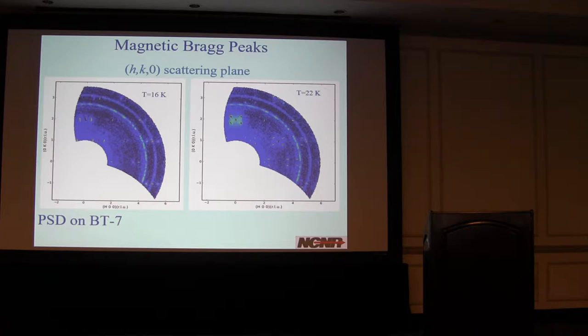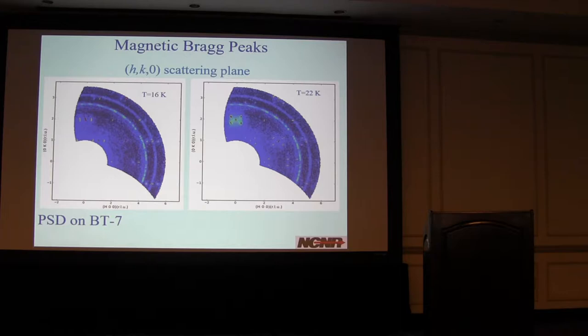There's also a magnetic ordering temperature that is quite field dependent, up to 14 tesla. So we started looking at a single crystal, and sure enough we found here at 22 Kelvin—just below the 26 Kelvin ordering—there's a peak in the center which is a structural peak, and then four incommensurate satellites surrounding that. You can see that at many different lattice vectors on this map of the scattering.